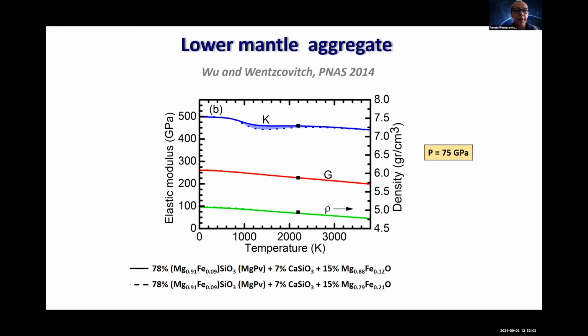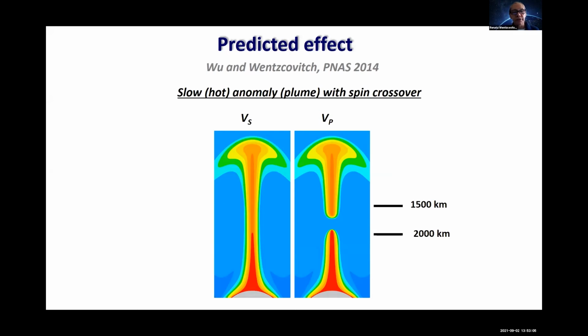They go in different directions, and that has a remarkable effect in a region of the mantle that is isochemical. For example, in a pyrolytic aggregate, if it's a uniform region of the mantle, a thermal anomaly coming from the core-mantle boundary to the surface, for example a plume, should be clearly seen in an S model, but the P velocity is going to be disrupted in this region of the mantle, because bulk modulus and shear modulus go in different directions, and VP becomes less sensitive to lateral temperature variations. This is a feature that is seen in some plumes in the mantle, but is it really seen in the mantle?